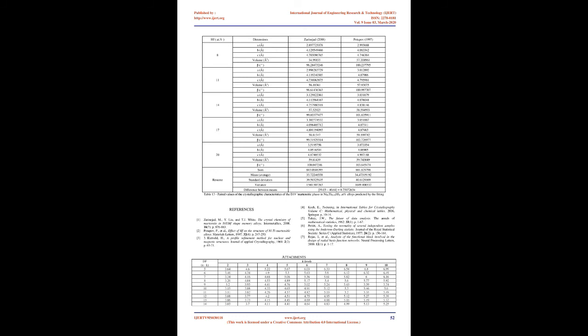These physical and mechanic properties, among others, are derived from atomic arrangement known as crystallographic structures, or crystalline structures. It can be mentioned as variables of these processes: the number of times that the bulk was melted, exposure time to the torch, type of material of the mold, efficiency of the applied vacuum, rotating speed of the copper flywheel in quickly solidified ribbons, etc. Hence, all the possibilities of variation and instrumental errors generate conditions of solidification which interfere in the microstructure of the alloys and obtained ribbons.